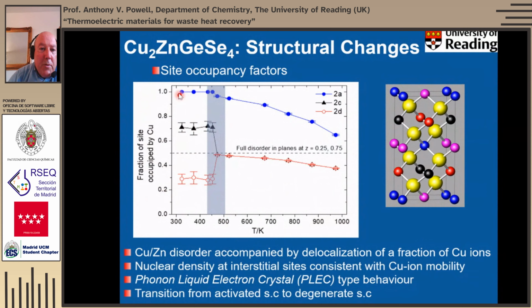So this is our room temperature structure. But when we heat it up, it appears to get to an order-disorder transition where these copper and zinc cations become fully disordered. So that would be this dotted line here. This would be 0.5 site occupancy factors in each. But at the same time, the actual total occupancy of that site falls away. And also, the occupancy of this site that was fully occupied by copper starts to fall off.